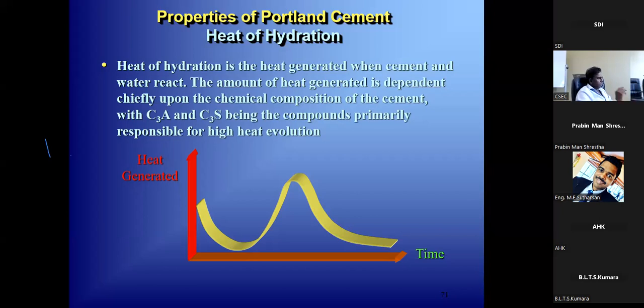So heat of hydration, 70 degrees, what do you do? You can use fly ash or slag, which will reduce the heat of hydration. They will increase the workability as well as reduce the heat of hydration. We talked about silica fume. Silica fume increases the heat of hydration because the silica fume reaction is very quick, and fly ash and slag slow down the reaction, so they reduce the heat of hydration. As engineers these days, not just concrete technologists, we need to understand these things. We had to approve the specifications.